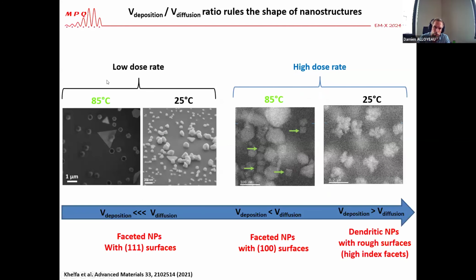You see that when you work at low dose rate, either at high temperature or low temperature, you are dominated by the diffusion speed, and you are forming nanoparticles that have mostly 1-1-1 surfaces, well-faceted nanoparticles. You have already seen that when you increase the dose rate at low temperature, you grow rough surfaces, dendritic nanoparticles, because you are dominated by the deposition speed. And when you work at high dose rate but high temperature, you reach this intermediate regime where you start forming those nanocubes. So I show you that playing with temperature gives you another possibility to explore the nanophase diagram of nanomaterials and better understand their formation processes.